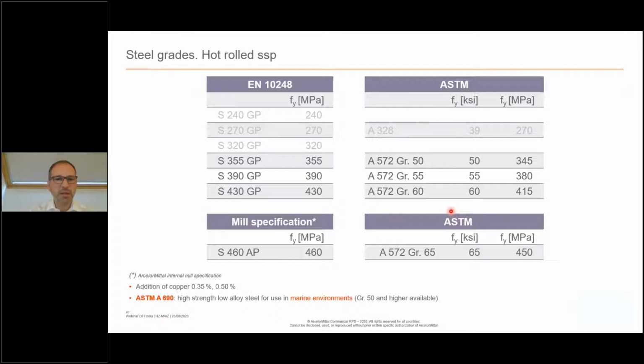And then we need to add some alloys in order to achieve the S390, as you can see here, or S430, or even the S460, which is not standardized yet, but will be in the next version of EN10248. We can also supply according to ASTM, and then you have similar steel grades, grade 50, grade 55, and 60, and so on. The yield strength is a little bit different, but this is something that you can also adapt.